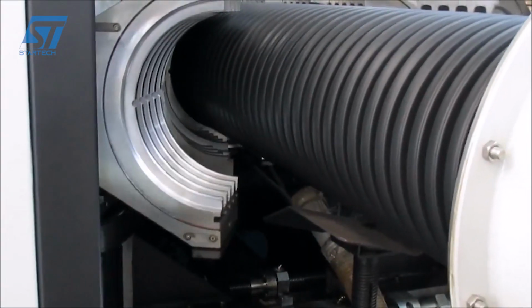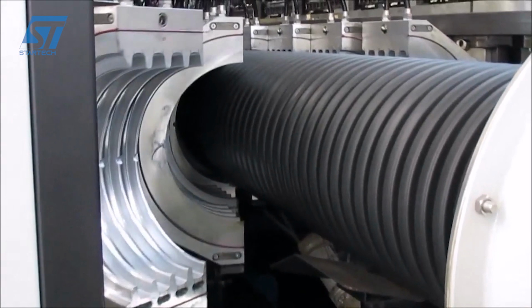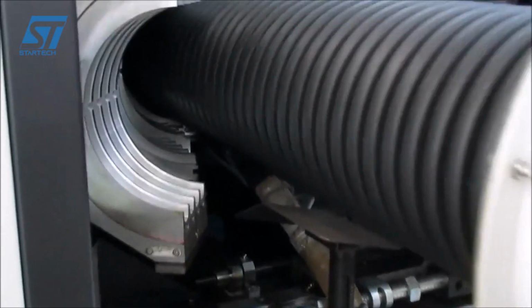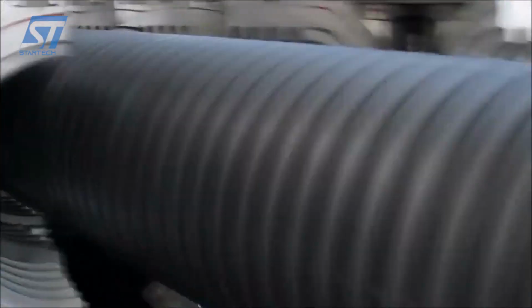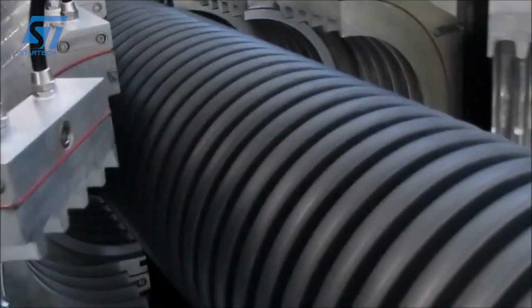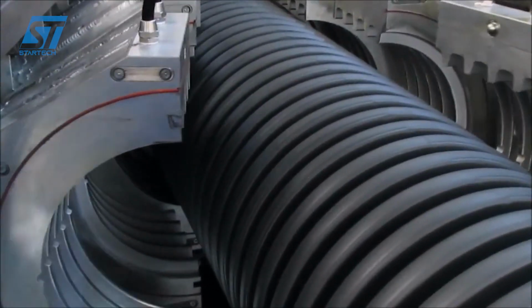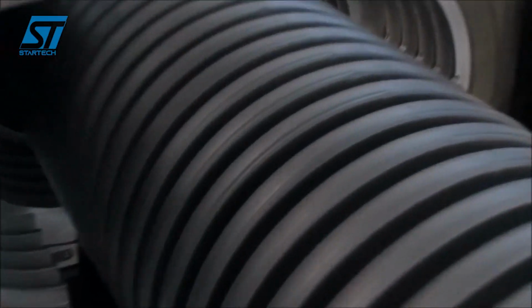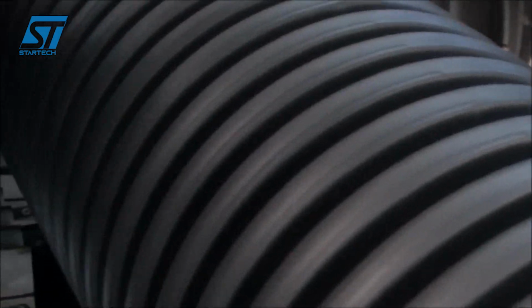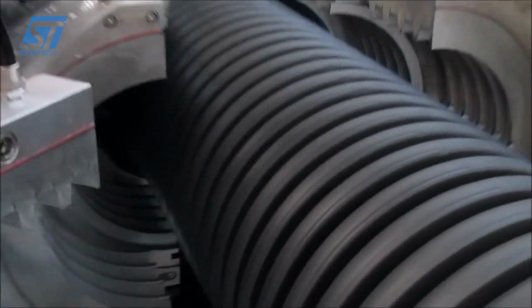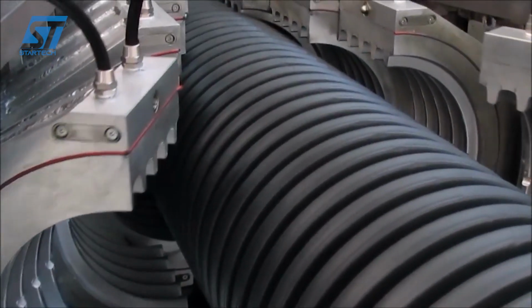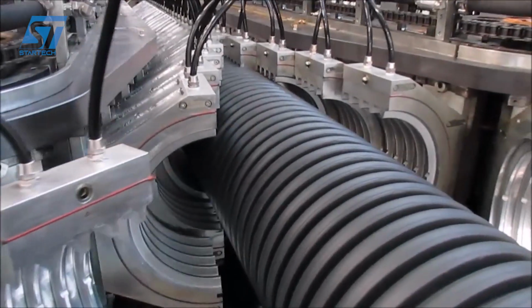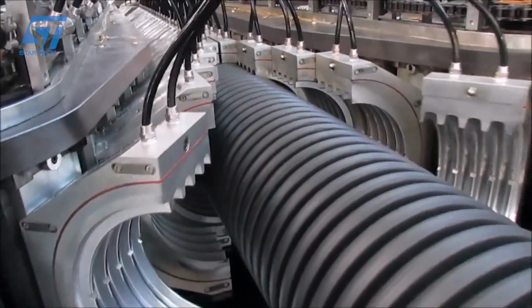The resin is divided into two streams. The inner layer is designed to be smooth to optimize the liquid flow. The outer layer is made thicker and reinforced to increase the pressure resistance. Co-extrusion ensures that the two layers are tightly bonded together, without separation under harsh conditions. Extrusion is the most important stage, determining the quality of the tube.